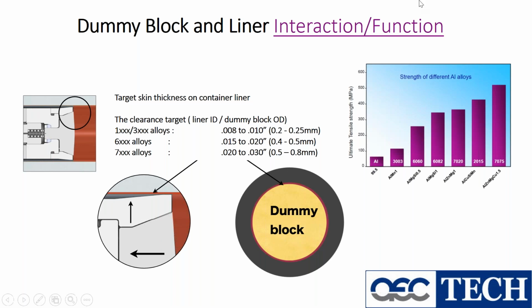So when we look at this, and you can see my mouse on the screen, 1 to 3,000 series alloys, this is the typical clearance that we would use on our tool. 6,000 series alloys, this is the clearance. And again, it has to do with extrudability and what minimum size gaps the alloy can pass through. Ergo, that's why when you use microtubing, you're using a softer alloy, because the softer alloy has an easier extrudability.